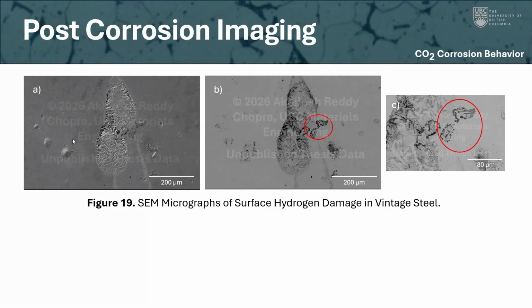So the clean steel without any blisters doesn't really show localized attack, which is expressed through the contrast in color, right? Compared to these blistered regions, if we look at figure B, which corresponds to the backscatter SEM images, it shows a defined etched microstructure. So we've been able to etch the surface with our corrosive electrolyte and reveal the underlying microstructure. And so it also tells me that if these regions are under high strain and we're more willing to oxidize, we can see that expressed through these images compared to the base steel.